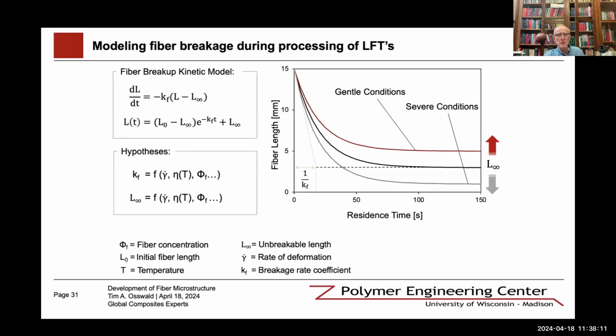decay function where we have the L infinity. So you can see the upper equation, basically the rate of breakage is proportional to the length itself. Obviously, the longer the fiber, the higher the breaking rate, and eventually, when the length reaches the infinite or the unbreakable length, then you've reached an equilibrium where you no longer can break the fibers. So the shear stresses occurring during flow are no longer high enough to break the fiber.